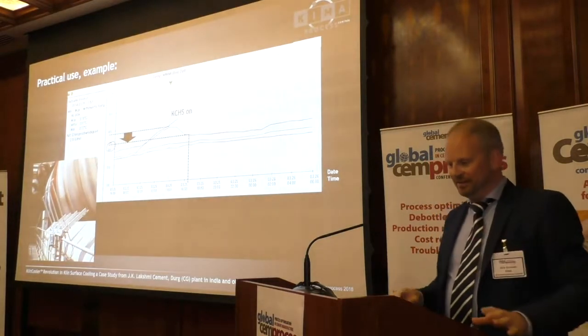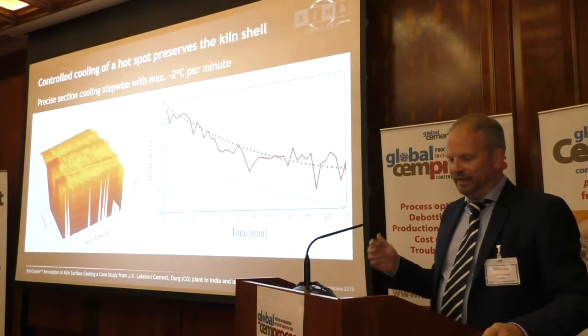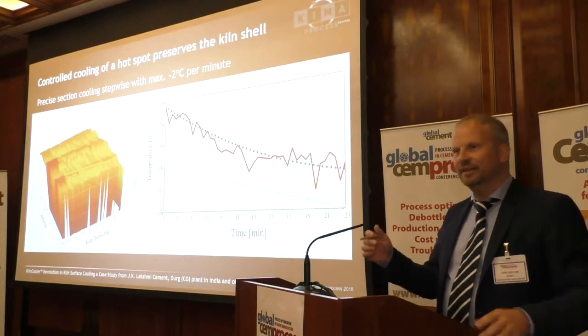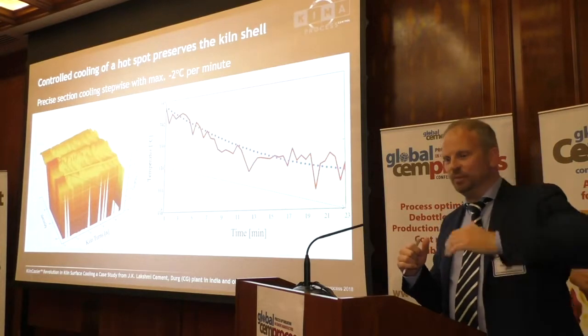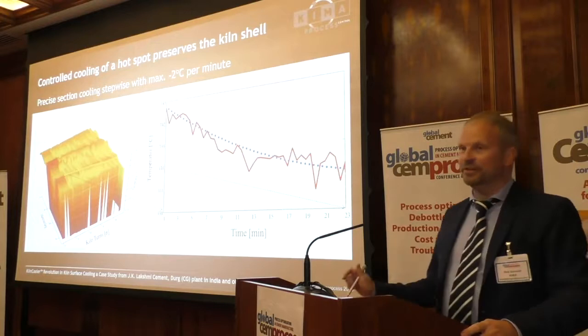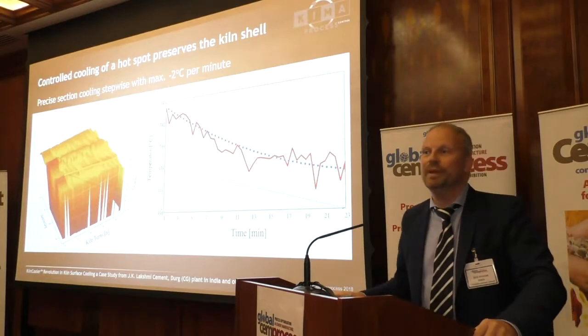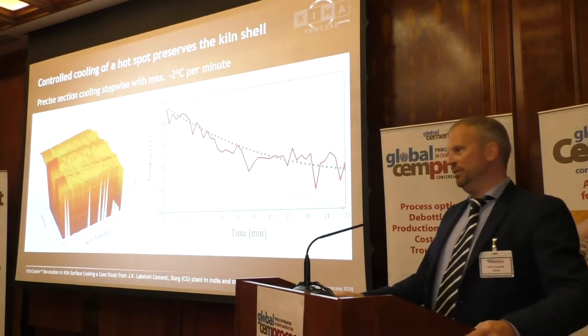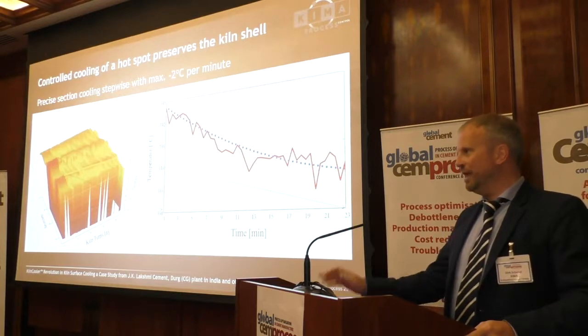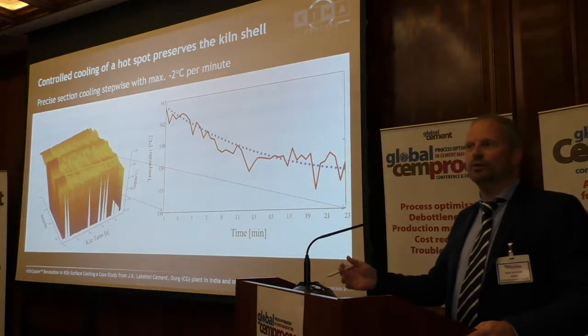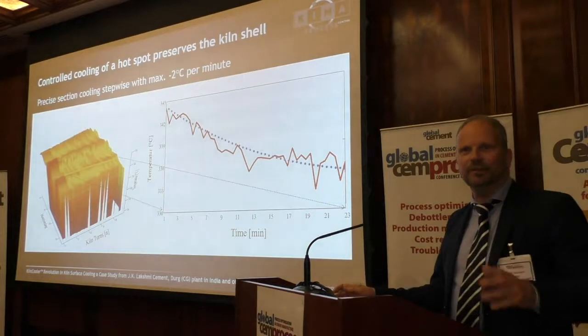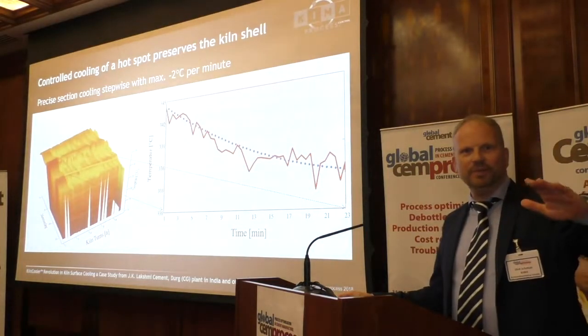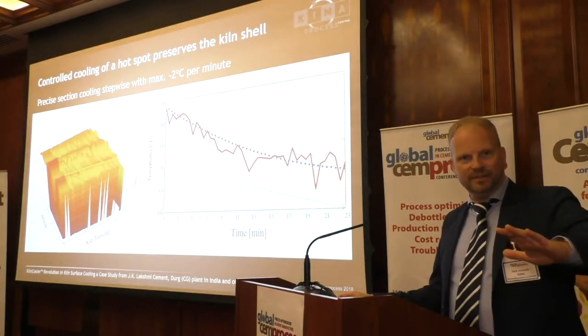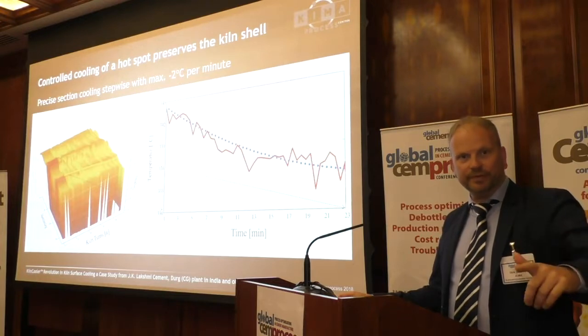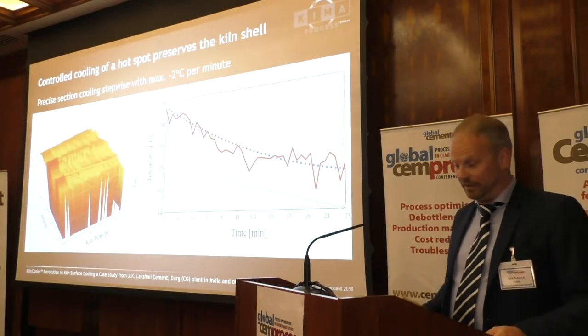The effect is, compared to an air fan I will show you later, that of course only this hotspot will be cooled. Another function in our controller is that we cool a maximum of 2 degrees per minute. Again, we have time. We don't want to shock cool, or make it hurry, hurry, hurry. 2 degrees per minute means a very stabilized situation for steel, refractories and new coating development.